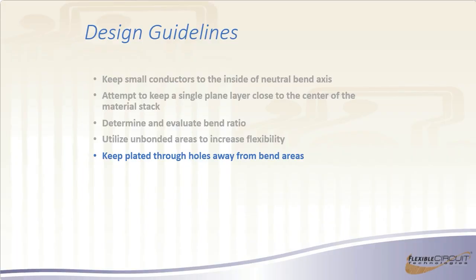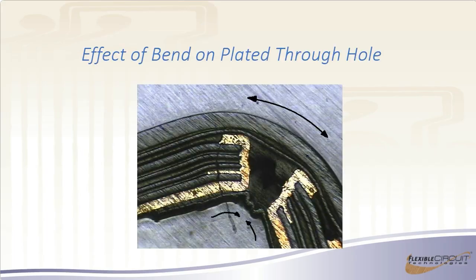You want to keep plated through holes away from bend areas. It's hard to calculate what happens between the layers with those tension and compression forces, but anytime you have a structure that bridges between them, it can be very problematic. This is a bend that I did right on a via, just to show that if you bend it tightly enough, you can actually distort the via. And in this particular case, it doesn't look like the via failed, but I wouldn't want to put that in any kind of life-saving equipment, that's for sure.